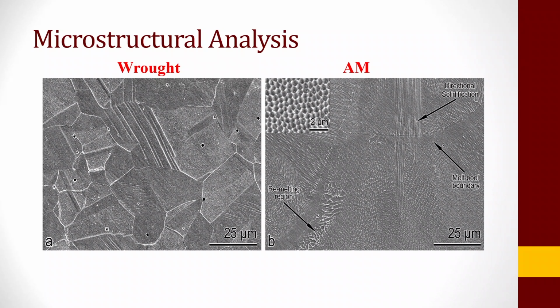But now when we look at the microstructure, you could see fairly large size grains in the wrought. However, when you look at the additively manufactured sample, you could see very small cellular types of structures. And then you could also see some directional solidification, or more like a columnar type of structure. You do see melt pool boundaries, and then we do have some remelting regions. However, in some of the regions which I focused on as an inset, it clearly depicts that a cellular pattern was observed during additive manufacturing. So in other words, the microstructure between the wrought and additively manufactured is completely different.